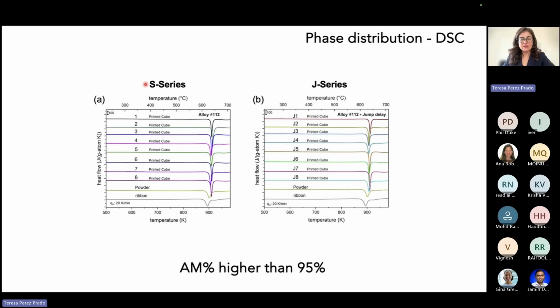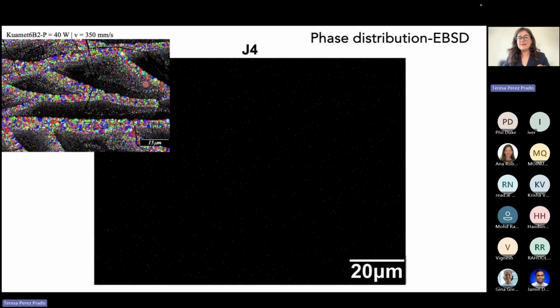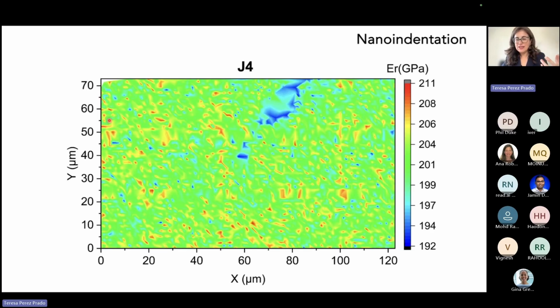We measured the amorphous fraction by DSC in all these samples with the new alloy, all these processing conditions. They were all higher than 95%. And we also use EBSD to check. Here is a representative map. It's completely black. I always say that I spent all my career investigating nice microstructures using EBSD. All I wanted in this project was to get black maps. And this is what we got. And here I put the image that I showed you before in KUAMET 6B2, so you can see the big contrast. So it seemed that we were able to make a fully amorphous material.